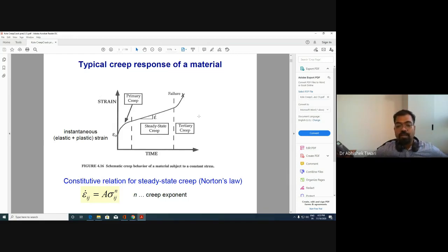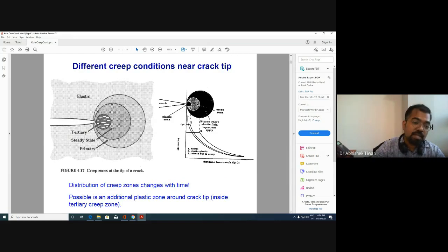We are not going to very high temperatures, because at those temperatures you have grain boundary sliding and usually you will have tertiary creep. The power law breaks down at high temperature. So let's talk about a moderate temperature where we can observe steady state creep. And if you increase the stress, as we discussed, primary creep might be suppressed, or steady state creep also can be suppressed.